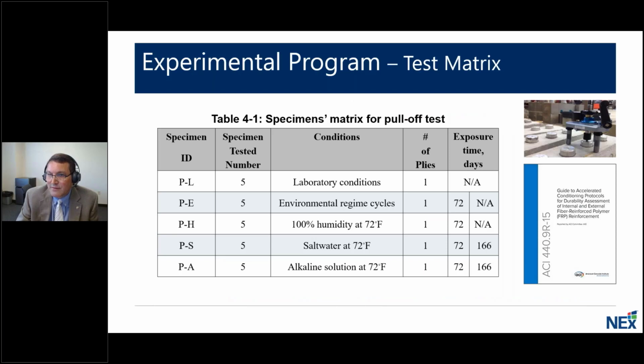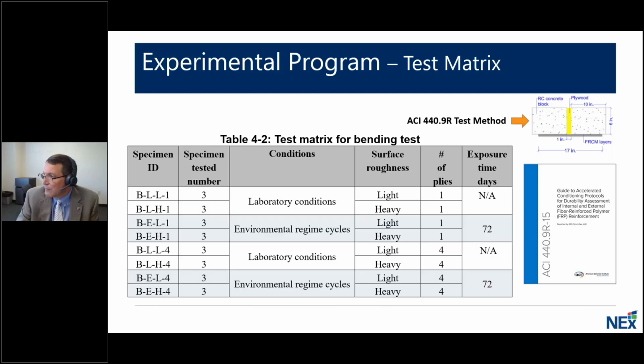For the pull-off test, as you can see here, we used 4 exposure conditions that we considered, and this included environmental conditioning cycles, 100% relative humidity, salt water, and alkaline solution, again using the ACI 440 document. For the bending test, again, 2 main variables were considered: the level of surface roughness and the environmental conditioning. Again, the ACI 440.9R document was used for specimen size and testing protocol.